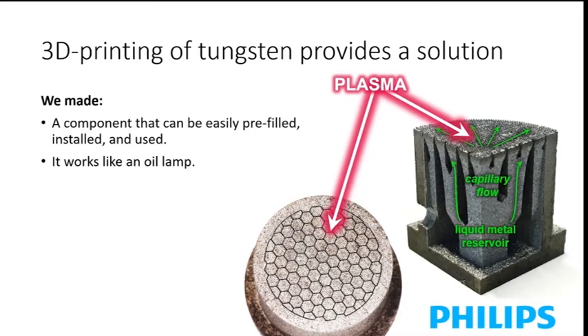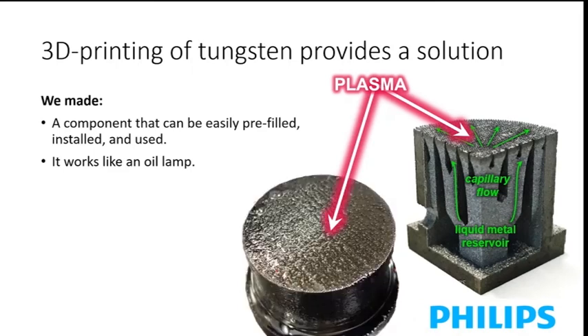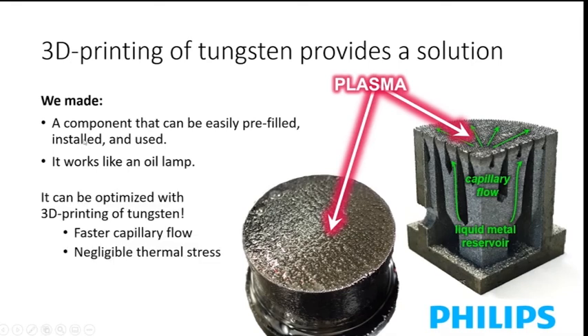And this works very practical. So you take a bunch of these, you fill them in outside of your experiment, you prepare them, then you put them inside your experiment, you use them until the liquid metal is depleted, and afterwards you fill them again, which looks beautiful, by the way. So here's a target filled with lithium in the glove box at DIFFER.